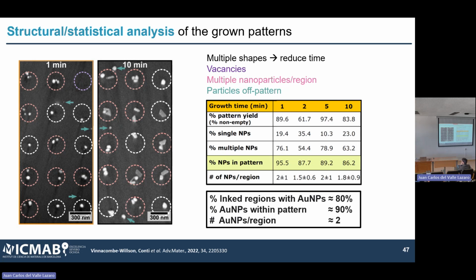And the second thing that is important to mention is that if you look at the products that you mentioned here that are actually different one from the other, you see spheres, you see triangles, you see truncated triangles and platelets, and you see rods. And these are basically exactly the type of particle that you would expect from a bad colloidal growth. So if you go back to the first paper about colloidal synthesis, this is exactly the kind of product that you would see when they were not controlling it. So this tells me that this system is, at least to a certain extent, behaving in a way that we understand, and that's predicted for us. And so I think that we can improve it.